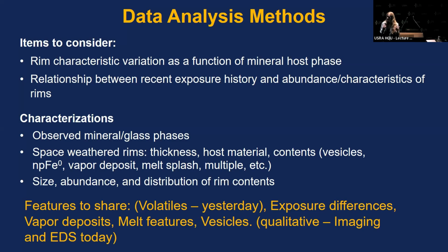And so when I say characterize, we're specifically looking at what the mineralogy is that we observe and the glasses, and characteristics of the space weathered rims, such as their thickness, the host material that they're on, their contents, and those contents can be single component or multi-component vesicles, nanophase iron particles, vapor deposits, melt splashes, sputter deposits.